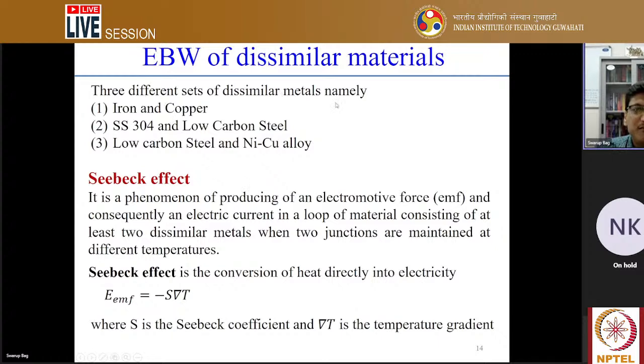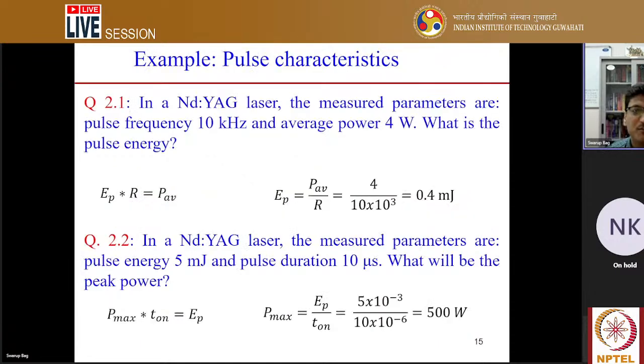Now, we can find these difficulties in the combination of these materials: iron and copper, stainless steel and low carbon steel, even low carbon steel and nickel copper alloy. So in this combination of materials, we can find this problem. Because of the Seebeck effect, according to Seebeck, some electromotive force is generated due to the temperature gradient of the two different materials. Here you can see the Seebeck EMF, the electromotive force, can be calculated as minus S into delta T. Here S is the Seebeck coefficient and delta T is the temperature gradient. So this generated EMF tries to deflect the beam in one particular direction. But if both are the same material, we cannot face these kinds of difficulties or problems associated with the electron beam process.